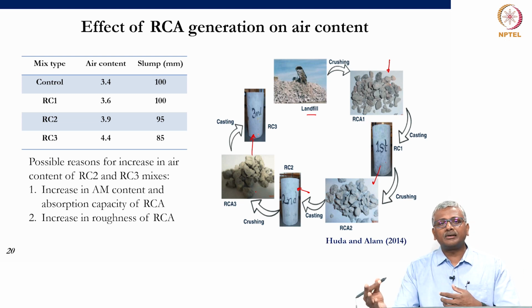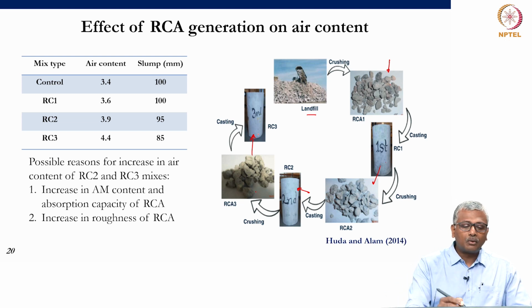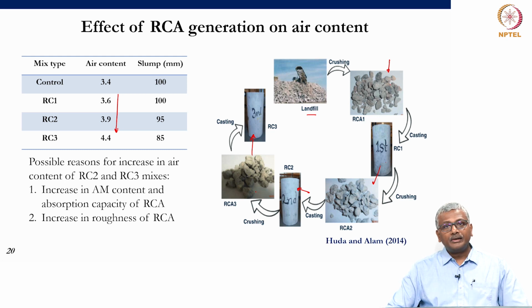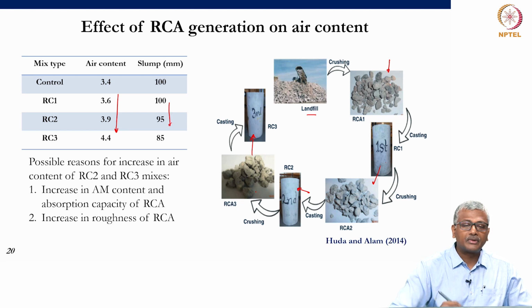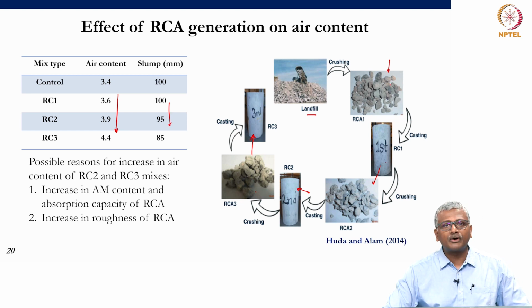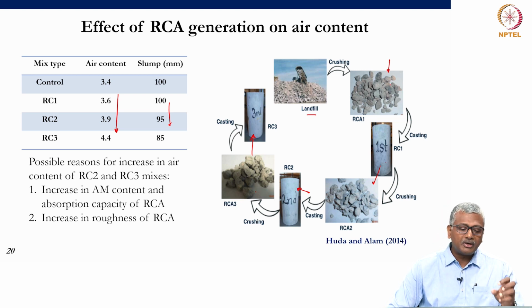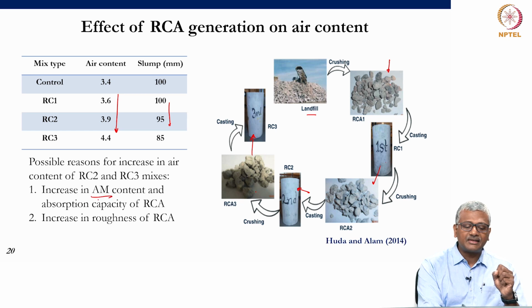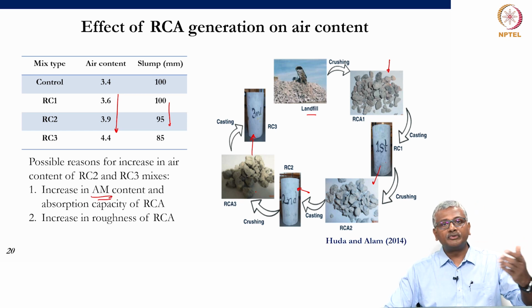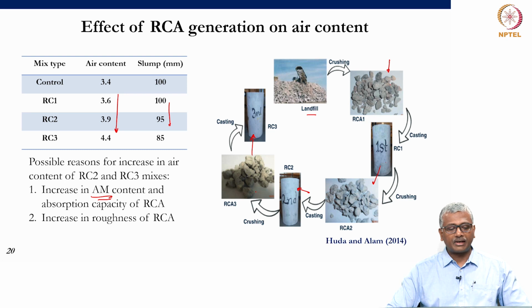What they wanted to see is how the property of the concrete changes when you keep changing this generation of the recycled aggregate. So, here what they saw is there was a minor increase in the air content as compared to the control. When you go for additional cycles of recycling, you tend to increase the air content and reduce the slump. Your slump is reducing somewhat because again there will be a change in the absorption characteristics of the aggregate, and you are probably going to be introducing more air. So, there will be an increase in the adhered mortar content as you go for further and further generations of your recycled concrete aggregate.